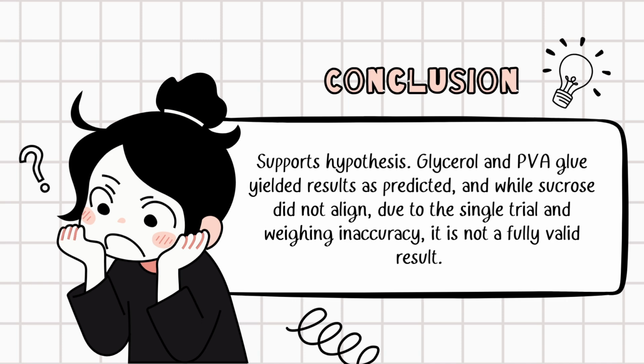The sugar sample was less consistent. Despite sucrose's tendency to promote brittleness, the flexibility remained unexpectedly high at 4, though its tensile strength was still low as expected at 2. These results demonstrate how molecular interactions shape polymer properties and emphasize the value of these findings for designing purpose-specific bioplastics.